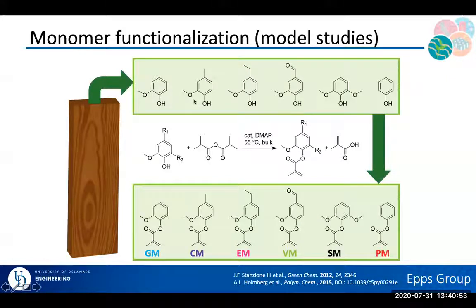For any of you that are familiar with the chain growth polymerization that I talked about earlier, there are no real functional handles that lead to chain growth polymerization in these molecules. So what I can do is a quick, one-step, relatively straightforward, easy, low cost functionalization to get these acrylate or methacrylate handles shown here, which I can then use as the basis for my polymerization to generate the molecule shown at the bottom. So now I can actually make methacrylate-based or acrylate-based chain growth polymers that I can use for further study.